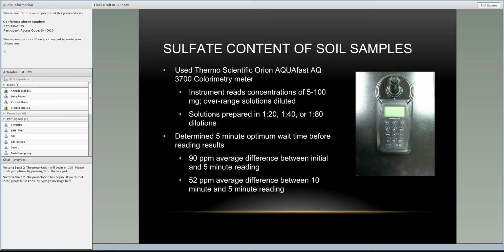The first time we started sulfate testing, we took the reading right away as soon as the sample was prepared, and we did it 2 more times after that. So we had 3 readings within a minute. We averaged those readings, and that was what we used for our sulfate results. However, as we were going through the process, we also took note of what the sulfate reading was at 5 minutes and what it was at 10 minutes.